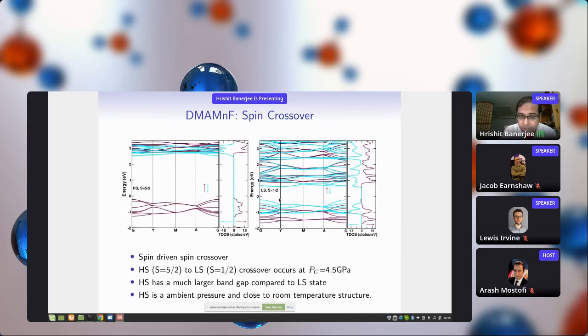Here the spin crossover is also between different spin states. So instead of S equal to 0 to S equal to 2, we now have S equal to 1/2 to S equal to 5/2. And this is also driven by a moderate pressure of 4.5 gigapascals. And the high spin state has a much wider band gap than the low spin state. And this is what generates the difference in piezochromism in this material compared to the hydroxyl ammonium iron formate and the dimethyl ammonium iron formate.